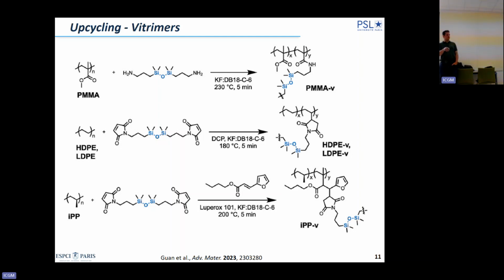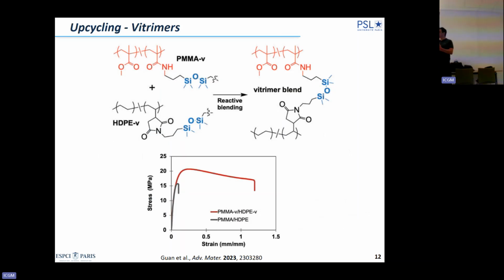So for PP, they use a similar approach, but it was necessary to add this molecule, which is, you see, an acrylate conjugated to a furan. The goal of this molecule is to react very fast with the radical created on PP to try to limit beta scission. I insist on the 'try to'. And then you can have a PP vitrimer. And they showed that, so they preformed these vitrimers separately, PMMA, PE, PP, and if you blend these materials in the melt by reactive processing, you can create a material with improved properties.